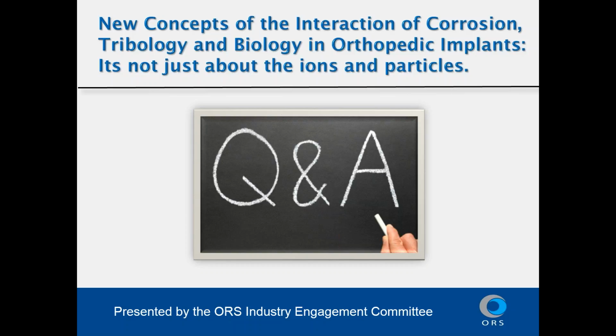I would point out, however, that there is a group in Australia. They have 2 publications out that I've seen. Kadosh is the lead author, I believe, and in there they showed inducing, I believe it was osteoclasts, in vitro to cause corrosion of stainless steel and titanium. And so I think there is some beginning evidence in vitro to document the phenomena that we're describing. I should also point out that there was just recently a paper published from another group confirming the observations that we've made on retrieved implants of the inflammatory cell-induced corrosion that just came out.